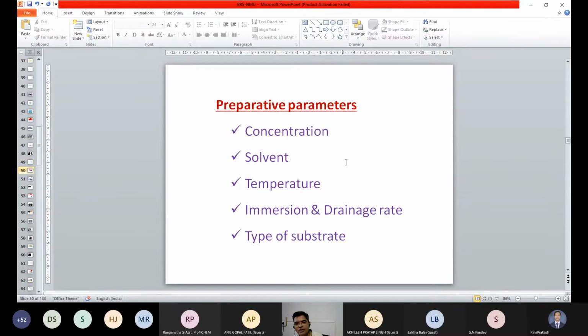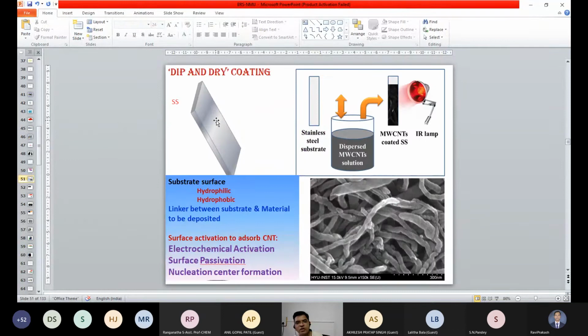So you can play with the concentration, what type of solvent you are taking, what temperature you are using, the immersion and drainage rate, and the type of substrate that you are going to use. So here we are using dip and dry coating, and depending upon the type of substrate, whether it is hydrophilic or hydrophobic, you can play with the carbon nanotube coating on the substrate surface.